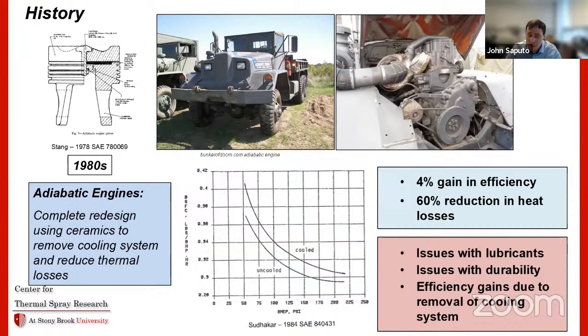At the same time, because they remove the cooling system, the temperatures get really high and you see issues with lubricants. The oil on the cylinder liner and things like that start to get too hot and burn. There are issues with durability from trying to replace all these complex components with ceramics. And the efficiency gains mostly came from removing that cooling system.